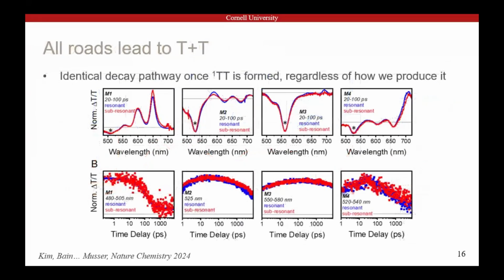But when we look at our films, we see that their spectral fingerprint and their dynamics are identical across the entire evolution that we can capture of this pair state, which tells us that, no matter how we photoexcite it, it is evolving in exactly the same way, whether it's separating into long-lived triplets like in this film, or rapidly recombining because they're stuck in traps like this film. This sub-gap absorption that we're pumping is truly representative of what the material does. It's not just a defect.